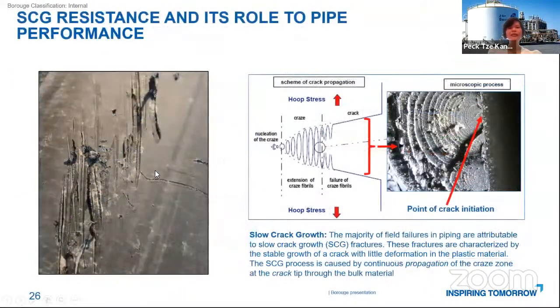Slow crack growth. Pipes are quite heavily handled on site, and sometimes we introduce scratches to the surface of the pipe. When that happens, even when the stress is removed, the notch created on the surface of the pipe will start to grow and penetrate through the pipe wall. This is because the stress at the tip of the crack is always higher, and it breaks the polymer chains over time. So a good material, or rather the more advanced polyethylene, has very good resistance to stress cracking. Today, the standards are talking about 500 hours by the notched pipe test. There's also PE100-RC, which Amos is going to touch on later, that has an even higher requirement for this property.